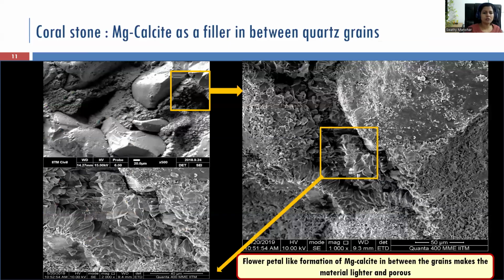When we look more into the microstructure, we found that the quartz crystals are surrounded by a lining called magnesium calcite, which had a flowery petal-like morphology, making the overall material much lighter and porous.